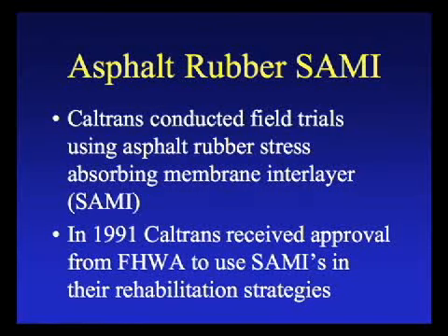So in 1992, we came up with the reduced thickness design guide based on performance in the field. We started to reduce all the projects from 1986 on. It only took 3 years for us to determine that we could reduce thicknesses and get the same design life. We did work with SAMIs, and this asphalt rubber chip seal used as a SAMI is an outstanding product, and I'll show you why a little bit later.